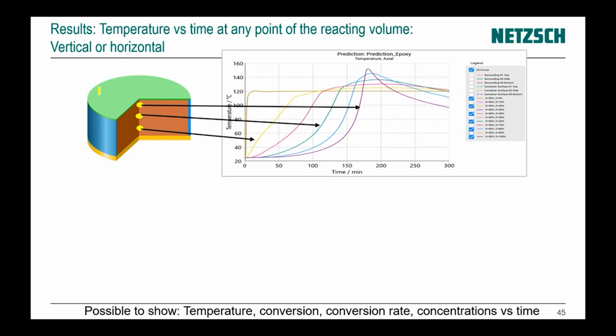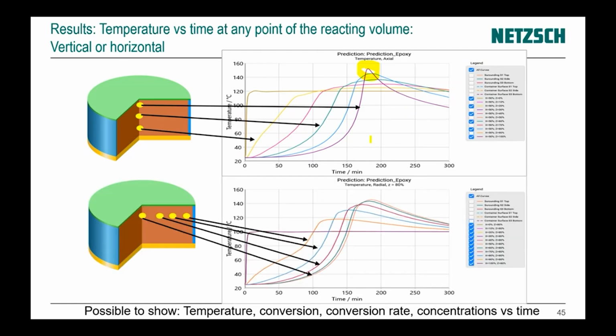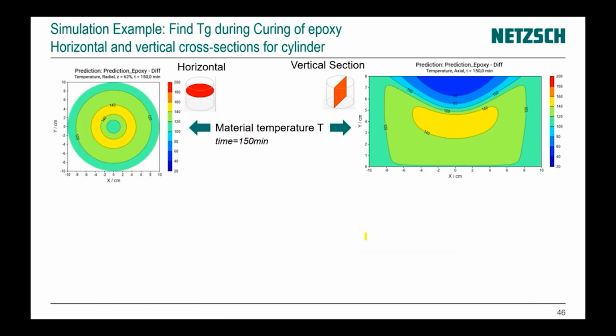For each point of our geometry, we can calculate a temperature. For example, here and here we have some increase of temperature because of the exothermic curing reaction. We can also select a different point in the radial direction. We can show the temperature, and the dependence on time for temperature, conversion rate, and concentration for multi-step reactions.